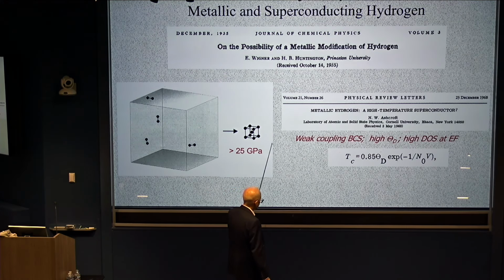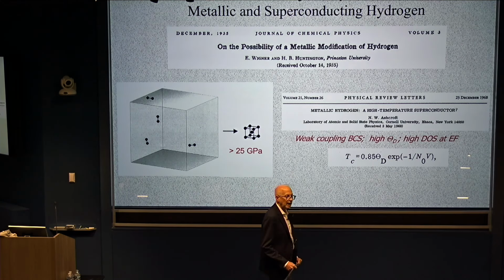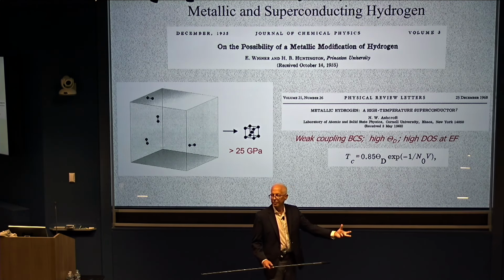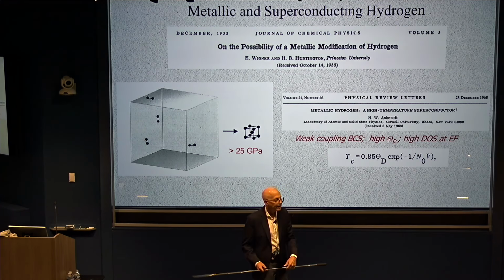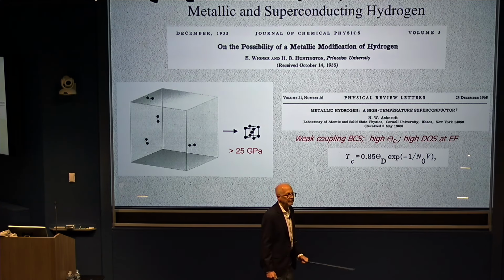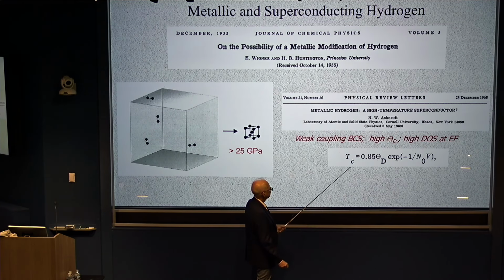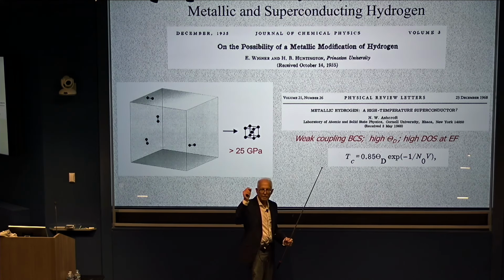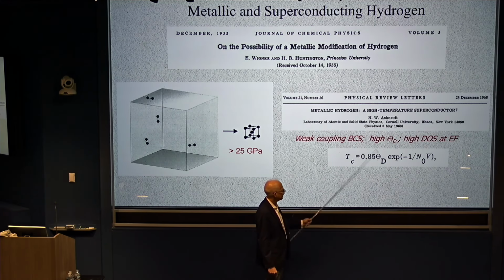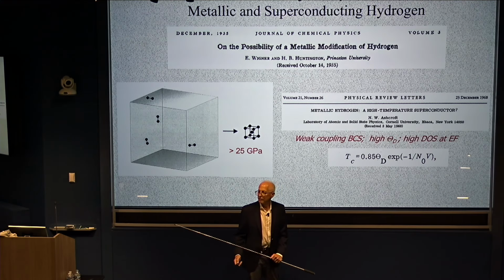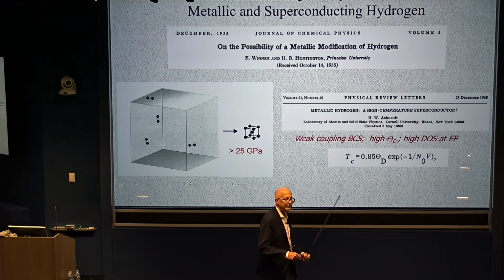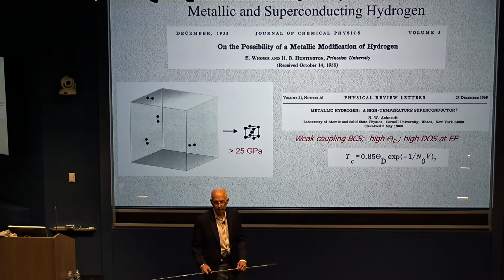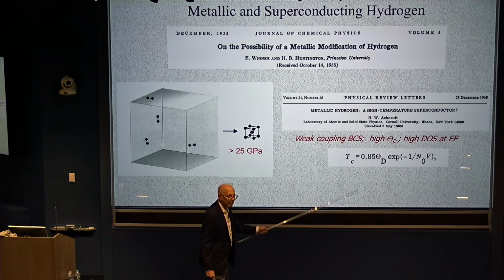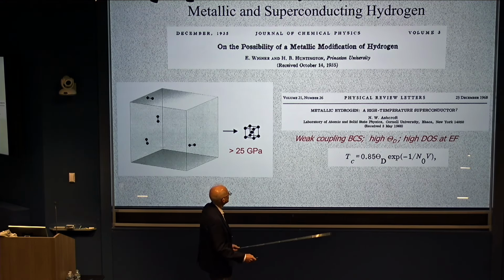And this was followed a number of years later by our colleague Neil Ashcroft, who said, okay, if we take this hypothetical state of this very simple metal, and you just apply the simple ideas of BCS superconductivity, it should be a very high temperature superconductor. It's got very high phonon frequencies because it has very light atoms. It has a high density of states, and it looks like it should have good electron-phonon coupling. So this really started the great excitement in trying to make metallic hydrogen. Vitaly Ginzburg had very similar ideas, who published about the same time.